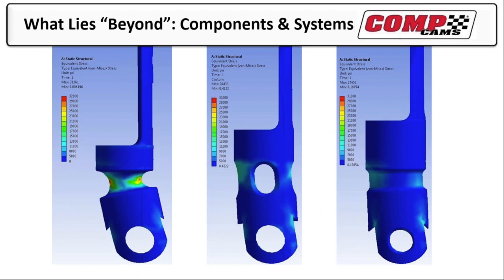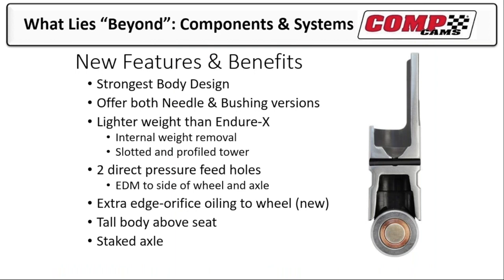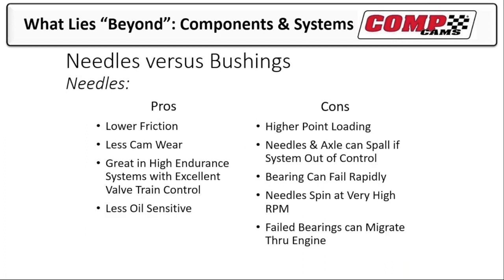So basically, if you look at our left, that's our original comp cams roller lifter design. And you can see when you start loading it down at the bottom that you get a lot of deflection there in the bottom. We came up with the Elite lifter that was better but still had some deflection. And then our new Sportsman was on the right. And you can see how we loaded it. We've really decreased what was going on. Basically came up, so you can see the pocket mill here. We've got a much lighter weight. We've got multiple oil paths. We've got 2 coming down the legs. We've got 1 coming from the skirt. So a lot of stuff going on in this deal.